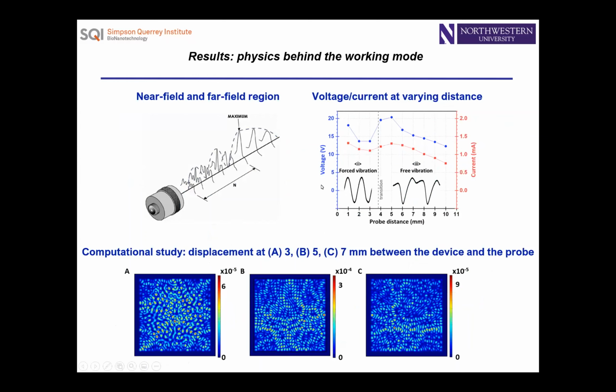Since our device aims to power something implanted inside the body, it is associated with implantation depth, which we should relate to the working distance from the ultrasound probe. Considering the ultrasound source itself, our 20 kilohertz has a maximum pressure level at 4 to 5 millimeters from the ultrasound probe. You can see the output performance goes maximum at that range, because there is a maximum pressure level which will highly oscillate the polymer film.